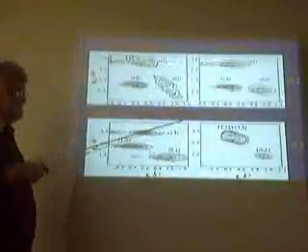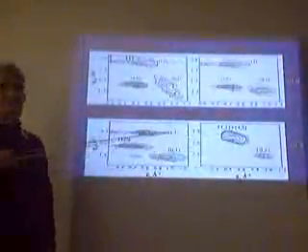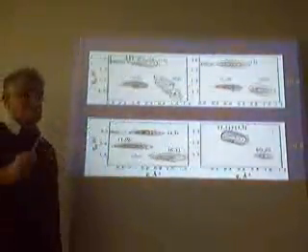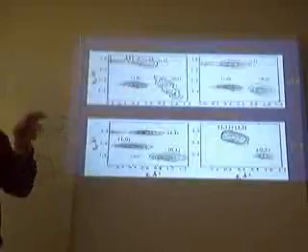There is some difference about the tilt angle of some of the chains in the pure L system, but it's clear that they are very similar to each other. Now, in the case of stearoyl glutamate, you see a very big difference between the DL and the L. So this is a racemic compound, and this is a spontaneous resolution in two dimensions, okay?